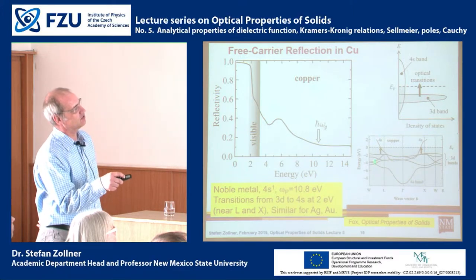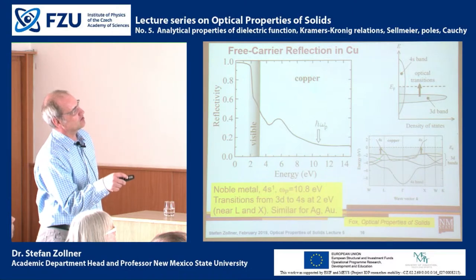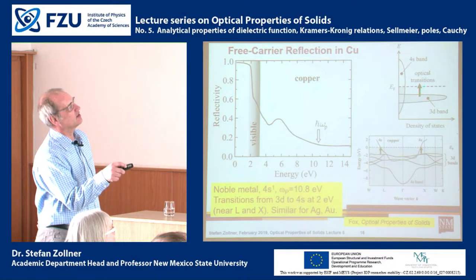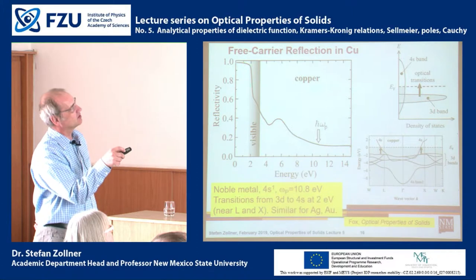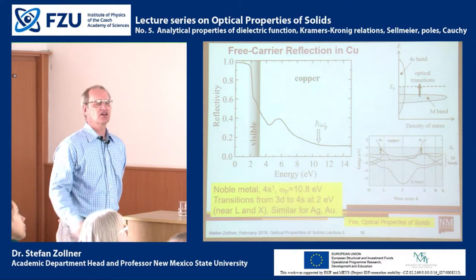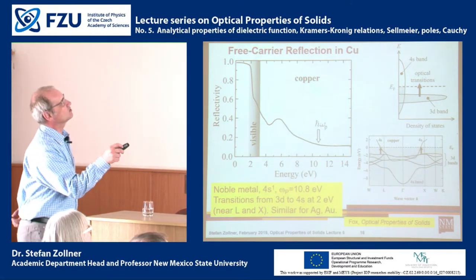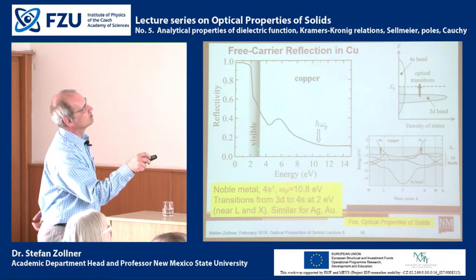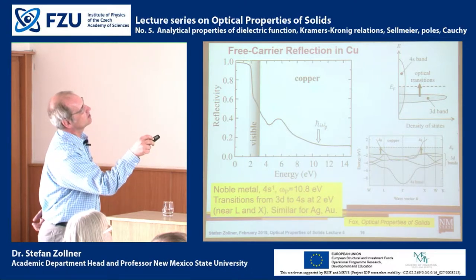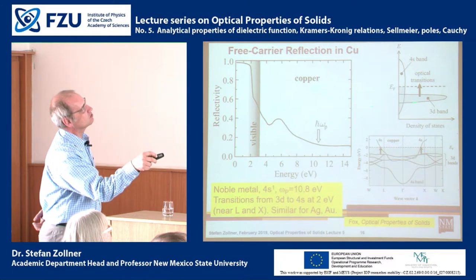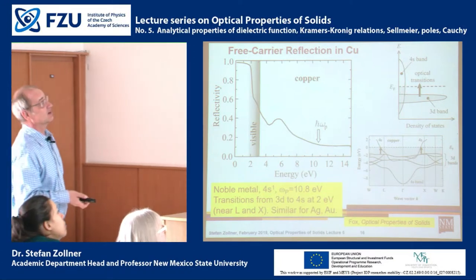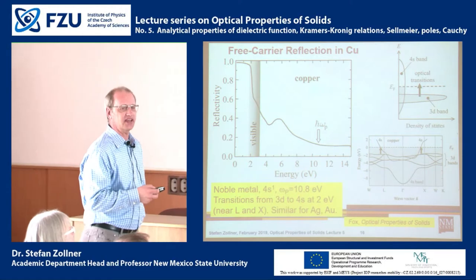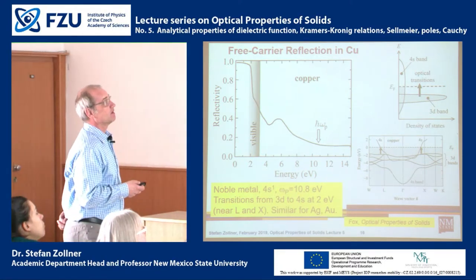We have the itinerant 4S bands and the localized 3D states. And then in copper, we can make transitions from the D bands into the 4S states right here at the Fermi edge. So if we measure this energy, if we measure the initial drop of the reflectivity, then that tells us how deep the 3D band is below the Fermi edge. So the 3D band is around 2 electron volts below the Fermi edge. We see that here. So this distance here, that's the binding energy of the 3D electrons. So at higher energies, the reflectance drops because we can make these transitions. And therefore, the reflectivity of copper drops at a much lower energy than expected from the Drude theory.